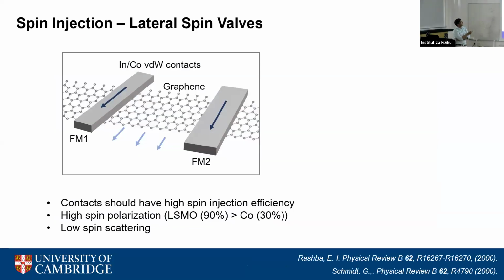So what we are making are these devices called lateral spin valves. This is a very basic test device where you just put two ferromagnetic contacts on graphene, and with an external magnetic field, you align these ferromagnetic contacts in parallel or anti-parallel orientation, and you measure the resistance of the graphene.